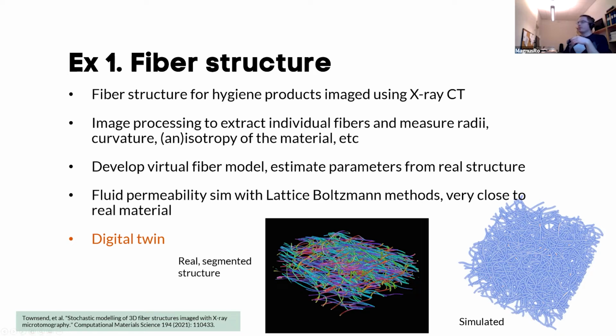We can look into whether the material is anisotropic, meaning different in different directions, or whether it's isotropic, the same in all directions. And using this type of information, we could develop a virtual fiber model where the parameters are estimated from the real structure. And we could also validate, by simulating the fluid flow and extracting the permeability, and also by measuring different geometrical properties, that this was something that was very close to the real material.